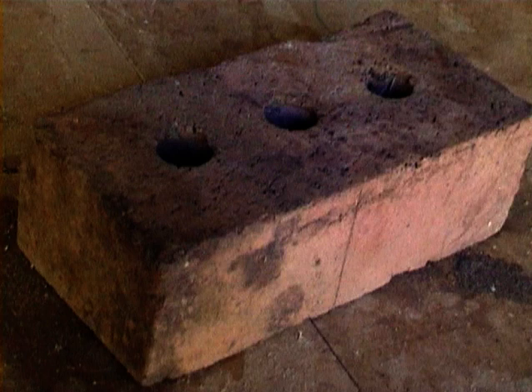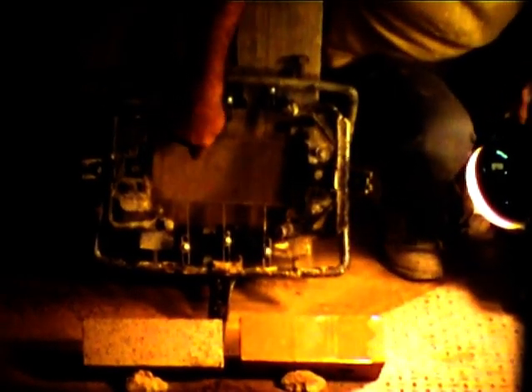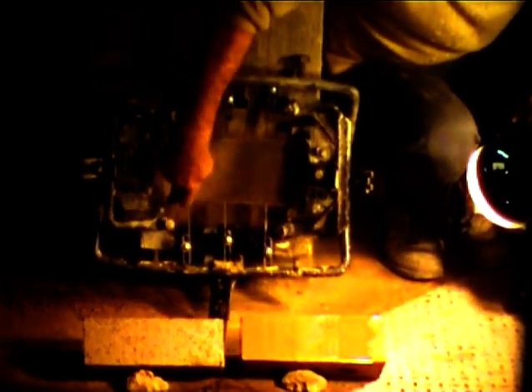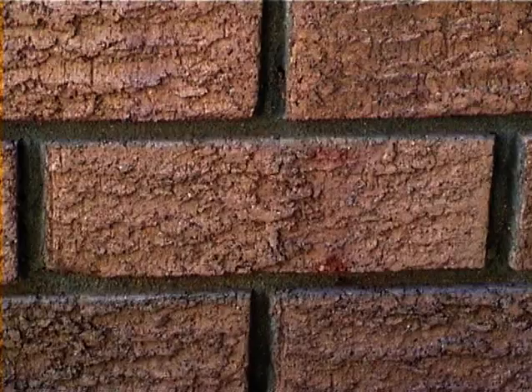This die of the extruding machine is capable of producing approximately 2 million bricks before being reconditioned. 3 rods are placed inside and at right angles to the opening of the die to form the 3 holes traditionally found in Monier extruded brick. A wire-framed apparatus can be attached over the face of the die to produce a patterned surface on the brick. This type of die is used to produce what is known as the rough cast brick.